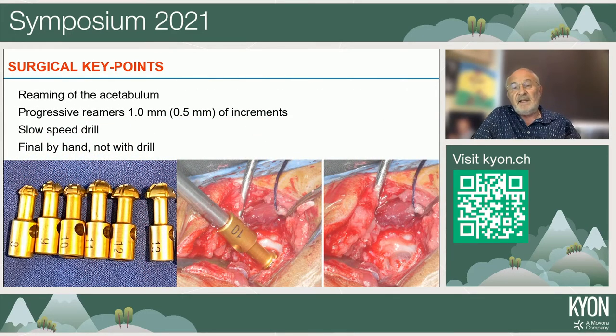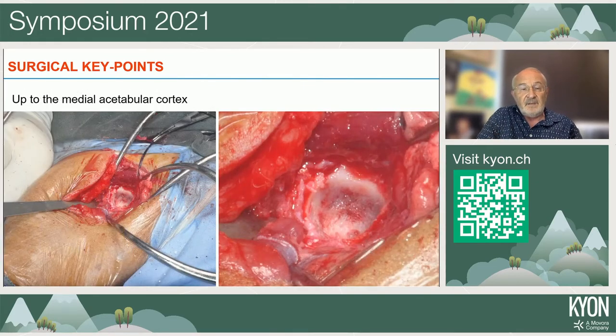Reaming of the acetabulum, I think, is the most tricky part because we have a very, very little tolerance to achieve a good press fit. For that reason, we have reamers with increments of 1 millimeter. And nowadays, new reamers are coming out with 0.5 millimeter increments, to be even more precise in our reaming, particularly for the final reaming, we should be at 0.5 less of the diameter of the cup, so we can achieve a good press fit, even in small animal.